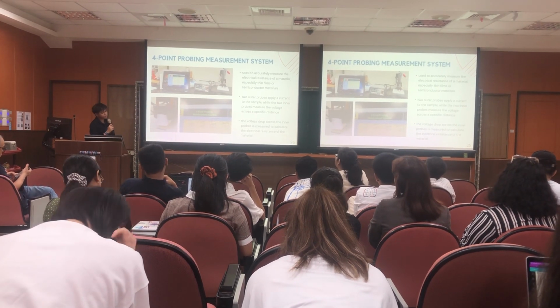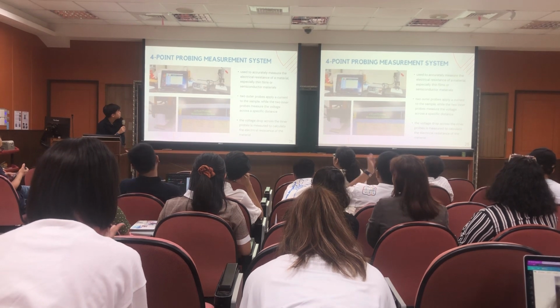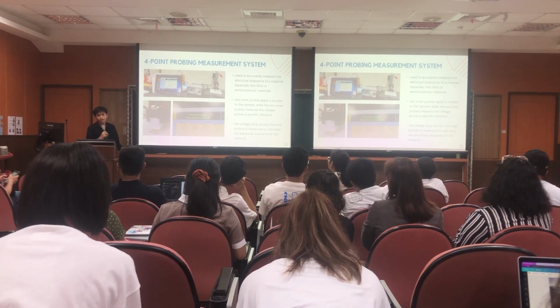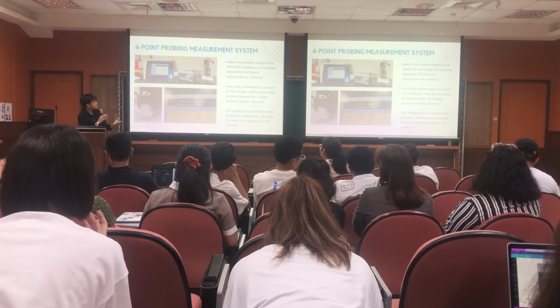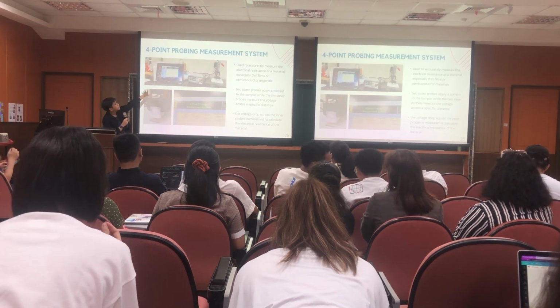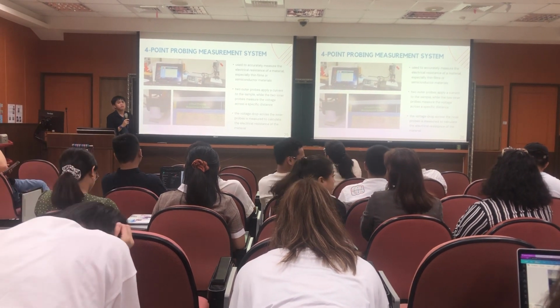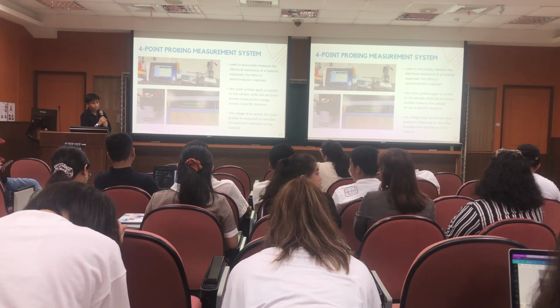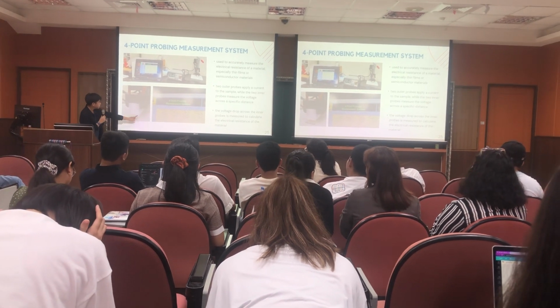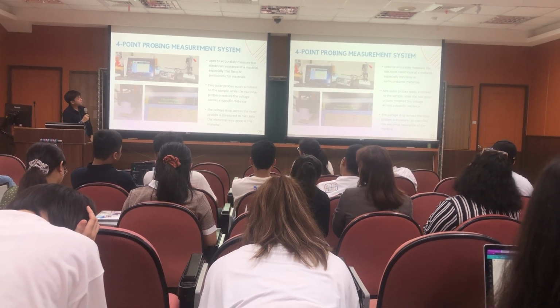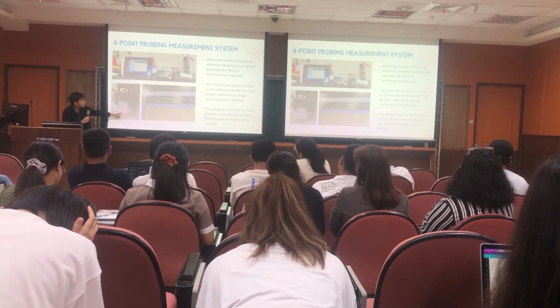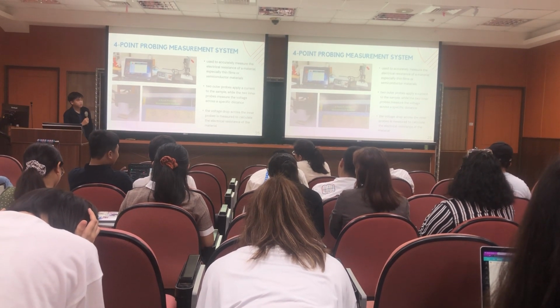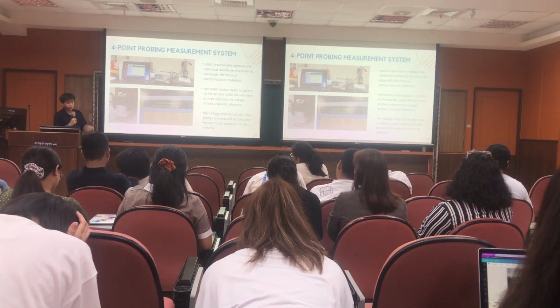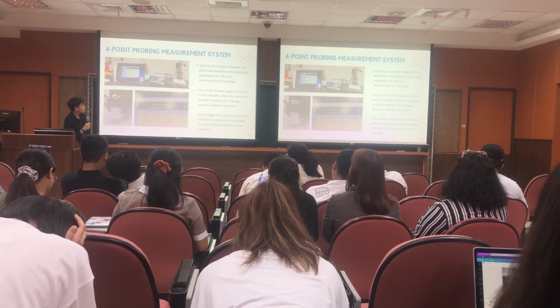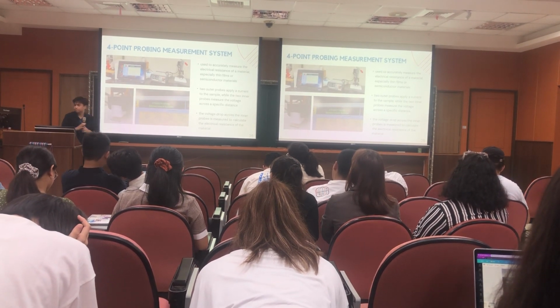The next piece of equipment I want to talk about is our 4-point probing measurement system. It's used to accurately measure the electrical resistance of a material. So in this setup, we use titanium oxide, which is a semiconductor. Here, I don't know if you can see it. It has 4 probes. The 2 outer probes apply a current to the sample, while the 2 inner probes measure the voltage across a specific distance. So the voltage drop tells us a little bit about the resistance of the material.